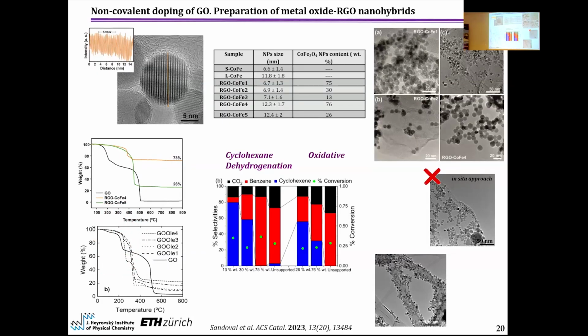This material was tested for the cyclohexane oxidative dehydrogenation. This is a reaction which is very important in terms of the production of benzene. And we can see that the material loaded with the small particles, which correspond to the left side, has a better behavior, better conversion, compared to the samples prepared with the large nanoparticles.